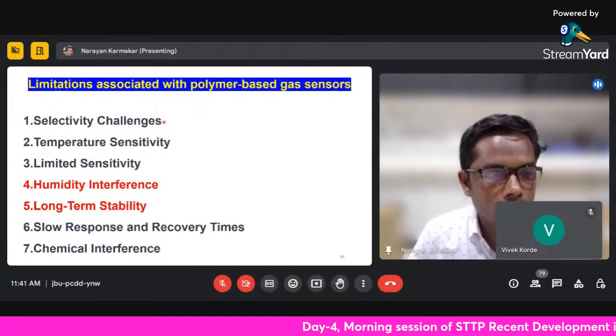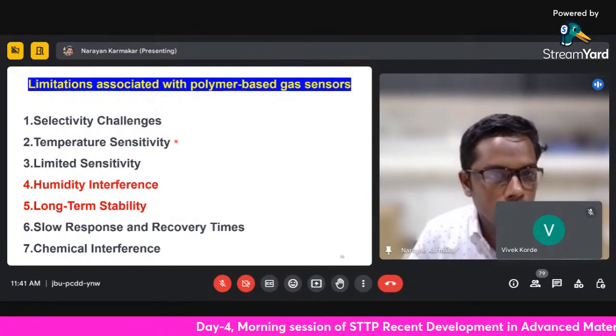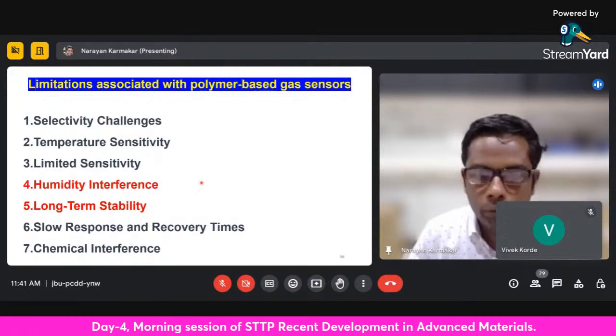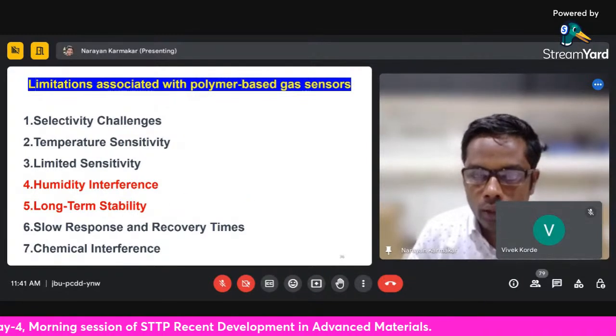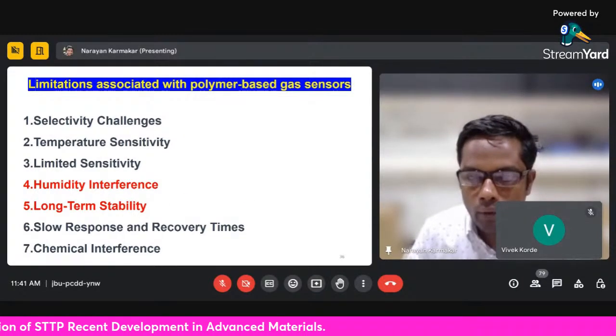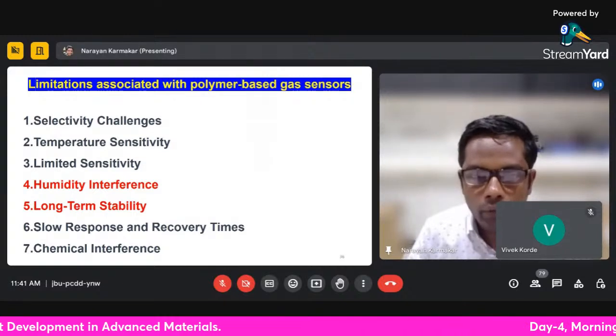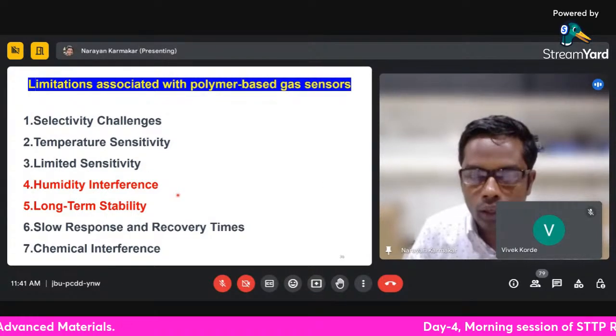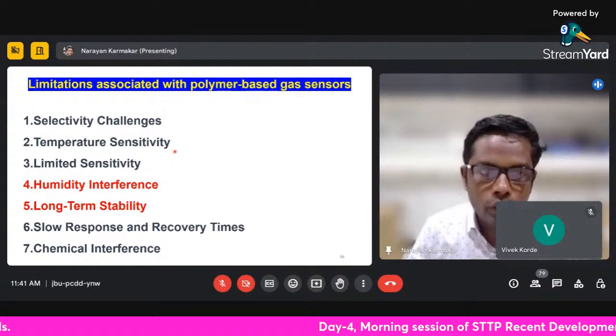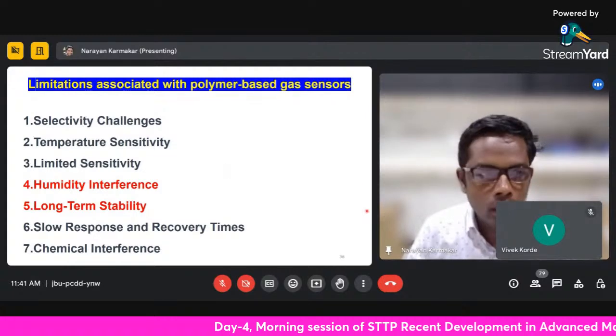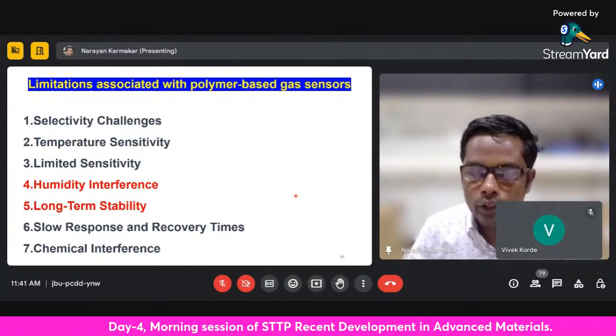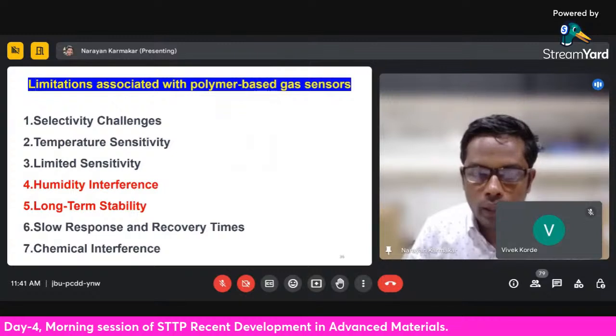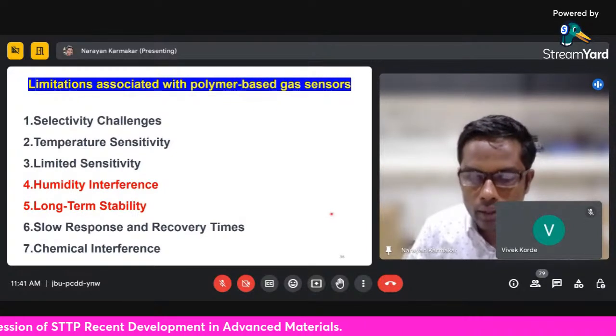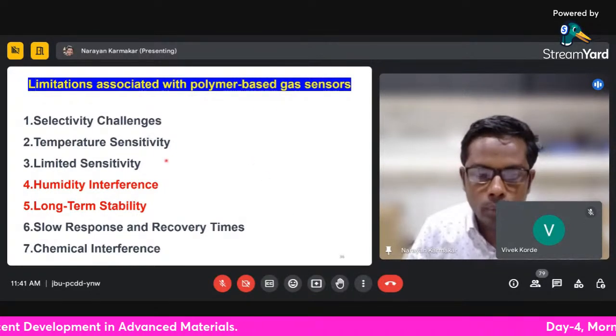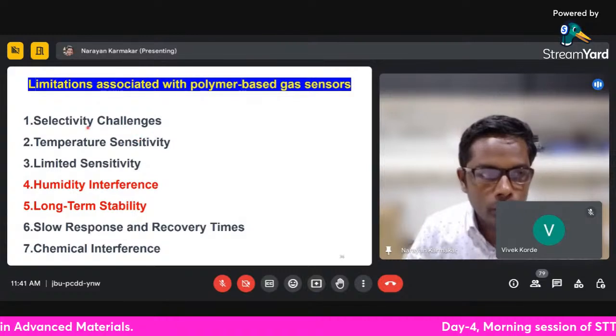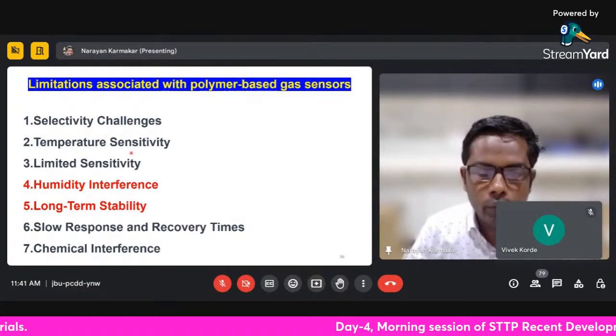The problem is this: the limitation associated with this polymer gas sensor is the selectivity challenges. We know that conducting polymers have several advantages, but they also come with certain limitations. Here are some common limitations associated with polymer gas sensors. The first limitation is the selectivity challenges. Achieving high selectivity for specific gases can be challenging for polymer-based sensors. So what is the solution for that? To increase the selectivity of the gas sensors.